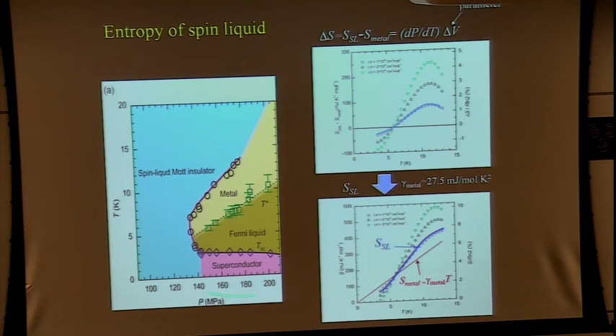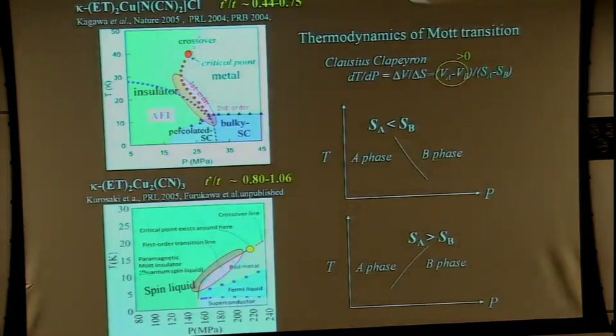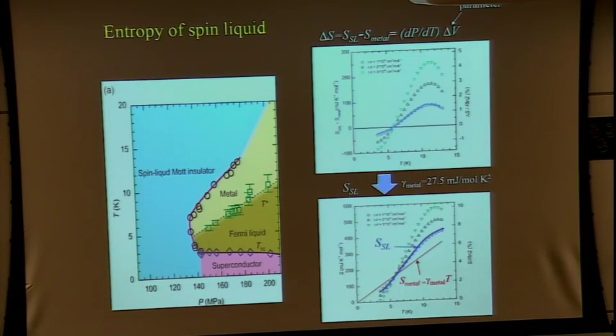Yeah, it's the same material. So the material is this one, the spin liquid material. The temperature is very low and precisely determined. This is the Mott insulator. It's a spin liquid insulator, and this is metal, and superconductivity occurs below 3 kelvins, and this superconductivity neighbors the spin liquid. Okay, this red curve is a fitting of the boundaries.